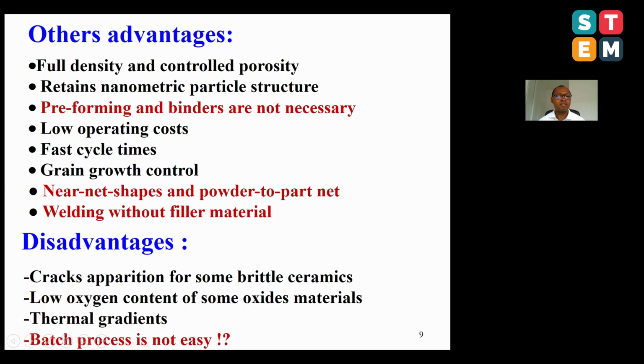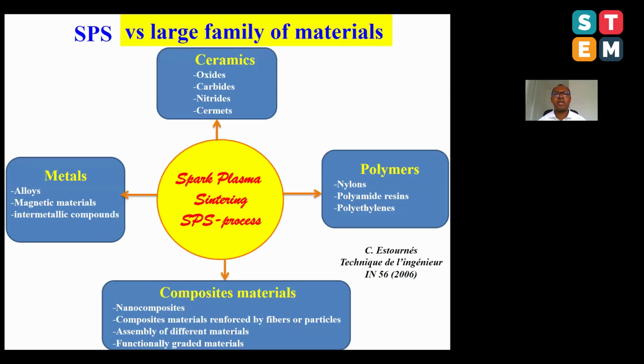But like any technique, some disadvantages exist, like crack appearance for some brittle ceramic materials, low oxygen content when you prepare oxide materials, because we use a vacuum chamber, which is not quite suitable for oxygen content, and also some thermal gradient. One open question is, can you really prepare batch processes easily using such techniques? Let's try to give you an answer in a few slides.